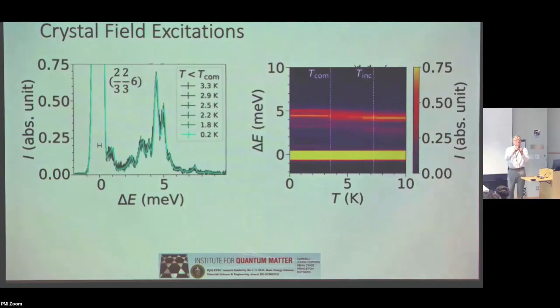What's basically happening is that in the incommensurate state, there's not a registry of the modulation of the exchange field with the crystal structure. And so each neodymium atom is in its own environment, essentially. It's phase-shifted in some funny way with respect to the exchange field. And so therefore, I'm going to find just a distribution of different crystal field splittings. These are all Kramers doublets, so they all get split as we come along, but each site is having a different exchange field. And so I actually get a very smeared behavior.